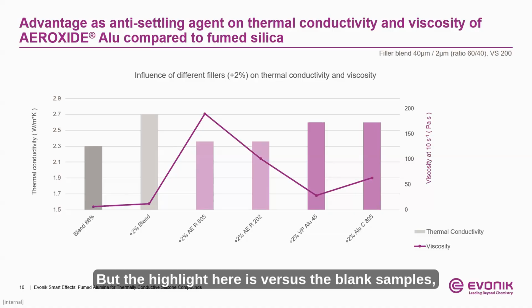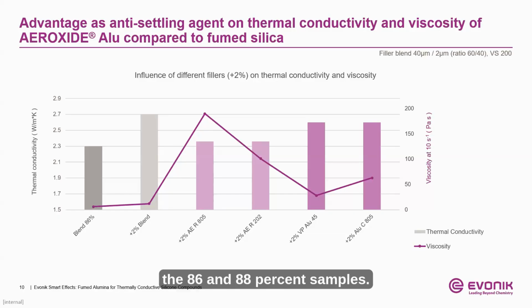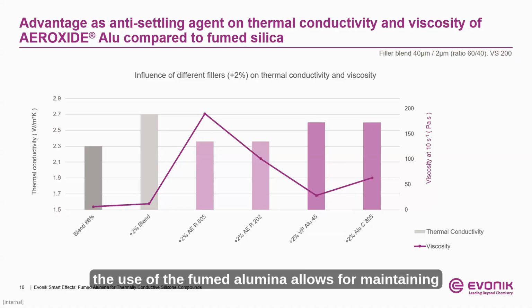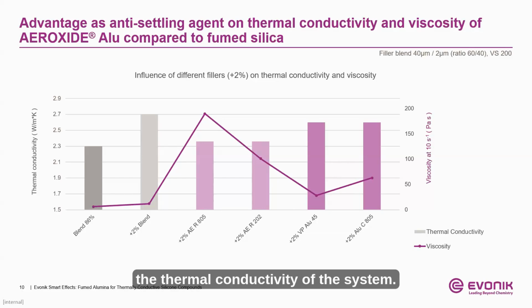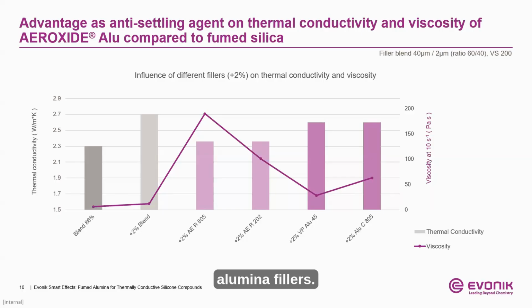But the highlight here is versus the blank samples, the 86 and 88% samples. Because alumina in general is high in thermal conductivity, the use of the fumed alumina allows for maintaining the thermal conductivity of the system very much on par with the blank at 88% loading, as both the blank and fumed alumina samples now both contain 88% of alumina fillers.